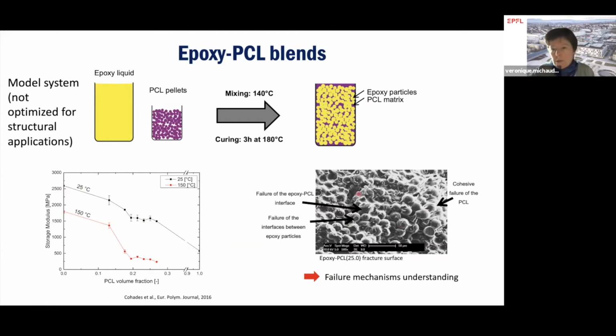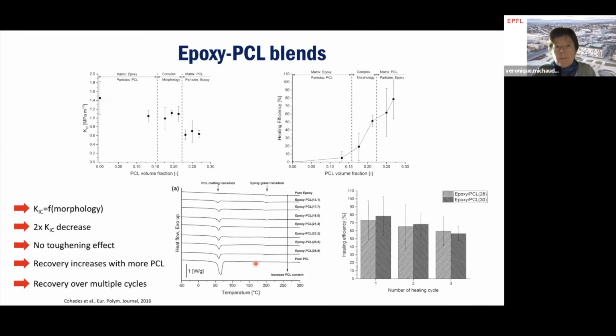We see also that we have this microstructure that was proposed and observed already by Luo, and that in the fracture surface we have all kinds of mechanisms taking place depending very much on the morphology of the blend. So we saw that if you increase the volume fraction of PCL, you get very good toughness properties for low volume fraction of PCL, but as you add PCL, you lose a bit in toughness of the material. But as you add PCL, of course, you increase a lot in terms of healing efficiency, which was a toughness recovery in TDCB configuration in our case. So there is a region where you would have something that leads to a decent healing, yet you don't lose too much in terms of the toughness of the material.